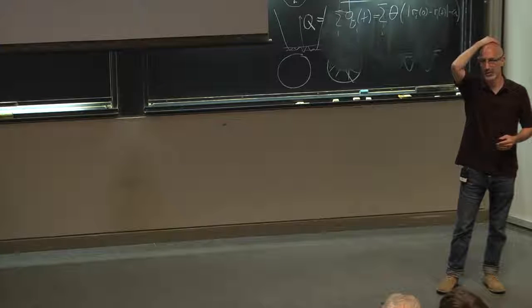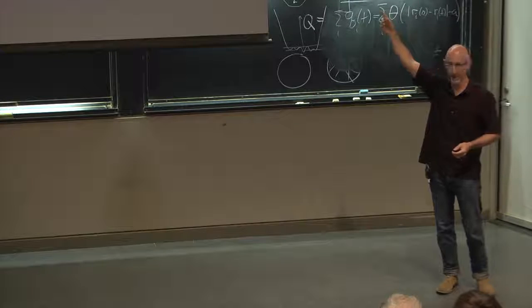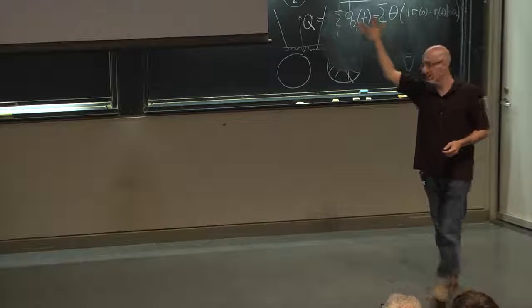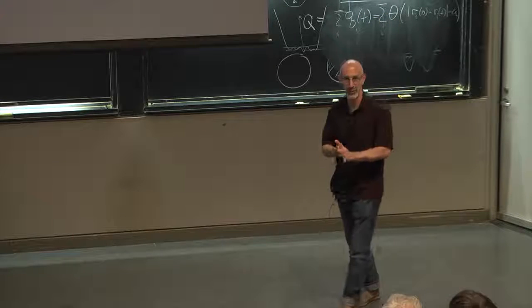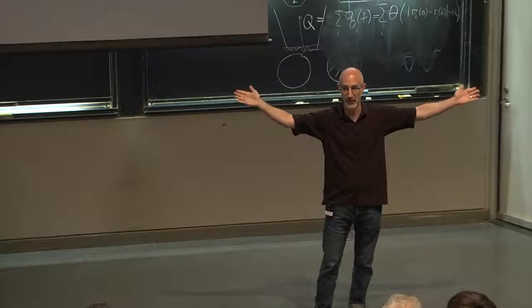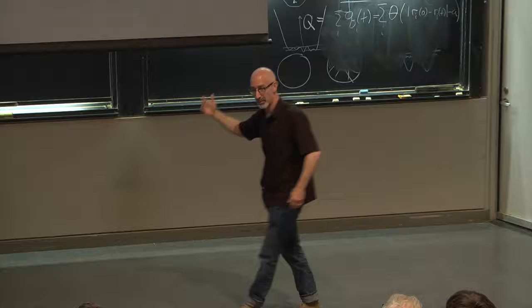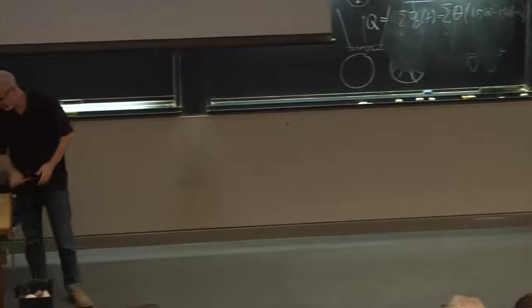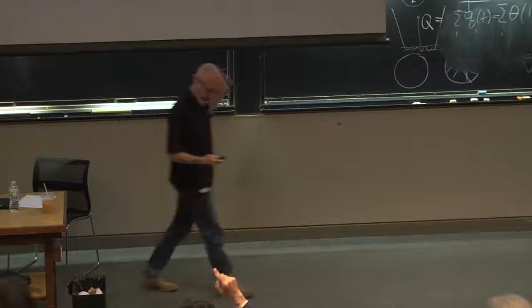So if you go to 30,000 particles, you find length scales that are about half as large as if you went to 100,000 particles. Ludwig's simulations here are 1,000 particles. So he got lucky, right? If you do 1,000 particles and you do this very crude fitting, you get about the right answer that you get from 100,000 particles, where you really have a very large box. So this is kind of a mess. And there are probably better ways to do this. But that is what it is.